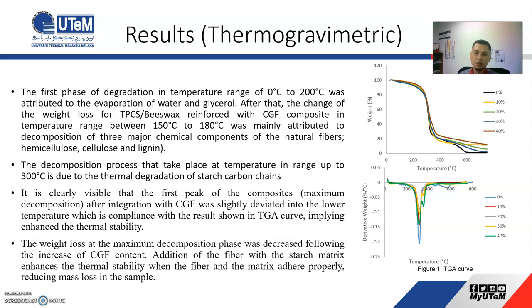So as a result for the TGA, as you can see from this picture here, the one with the higher percent of fiber loadings stays on the top, which means that these materials have better thermal stability as compared to the material with no fiber, which is 0%, on the bottom. Okay, so you can see here it's a good indicator which shows that adding the natural fiber is able to improve the thermal stability of the materials.